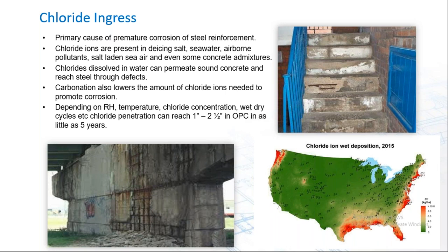Airborne pollutants, as I mentioned, salt-laden sea air. And even some concrete admixtures also contain chloride ions. These dissolved in water permeate sound concrete and reach steel through defects. Carbonation also lowers the amount of chloride ions needed to promote corrosion. And depending on relative humidity, temperature, chloride concentration, wet and dry cycling, etc., chloride penetration can reach 1 to 2.5 inches into ordinary Portland cement in as little as 5 years. And typically we're talking about only a 2-inch cover on reinforcing. So you can see how aggressive this can be in really creating a problem for concrete structures.